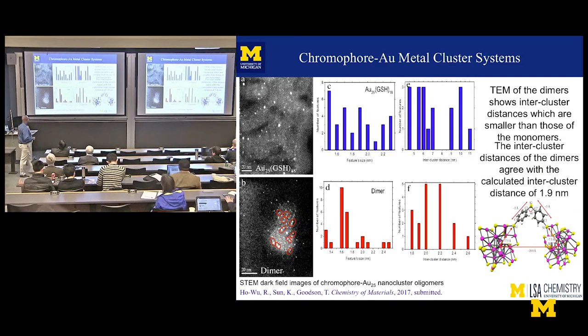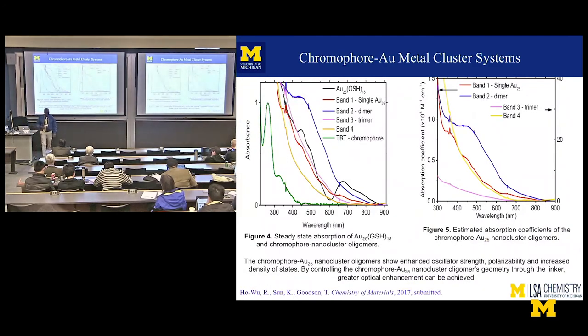Kaisun, from our facilities unit over in engineering, was really interested in doing TEM on these structures. He did TEM for a previous paper with Nuranga, which I showed you already, on the gold 25. He did that again, and then tried to compare the spacing between these clusters with this structure here, saying that the spacing should be smaller if you bring them in by a single dye molecule. Then he used this histogram approach to prove that he had actually seen that. So, kind of cool.